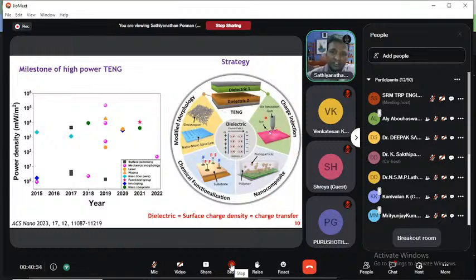So there are many strategies that have been applied, and because of these strategies, they have achieved almost more than 500 watts per meter square. In a recently published paper in ACS Nano, they reported 500 watts per meter square. So using a small device, 3 by 3 centimeters, you can actually produce this much energy, which is quite enough to power up your laptop, your mobile phones, and other small electronic devices.